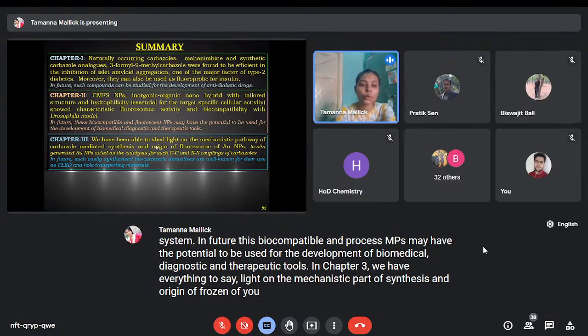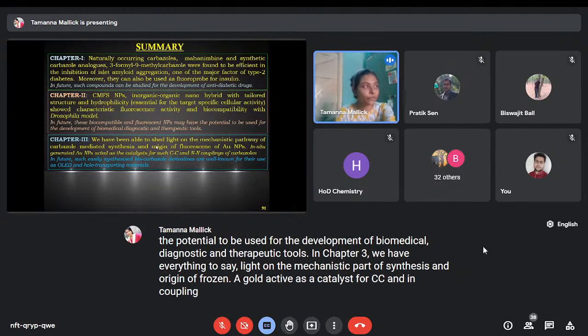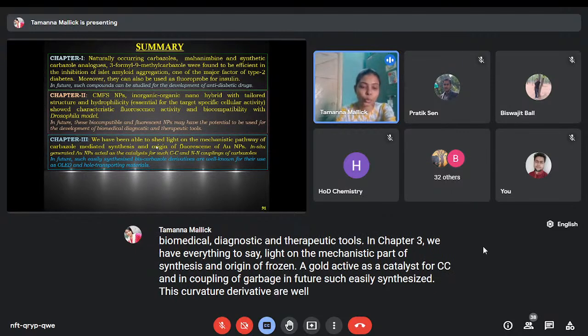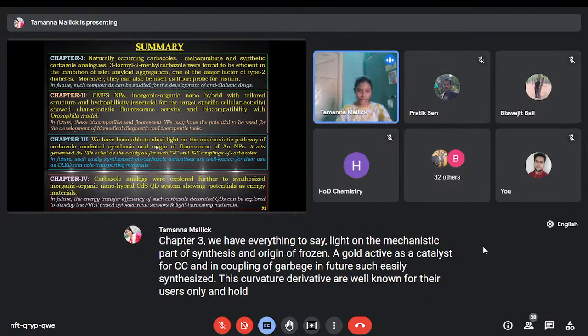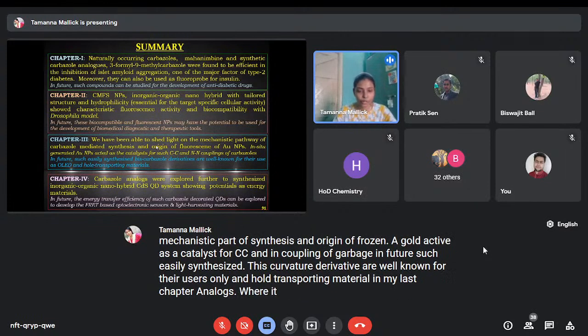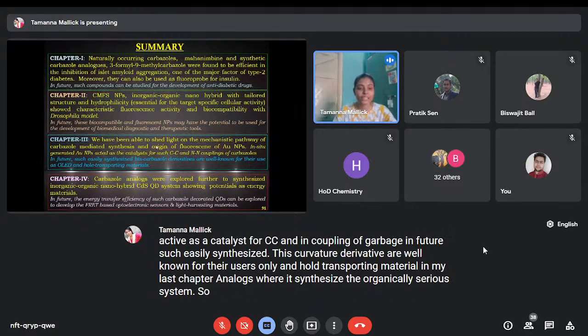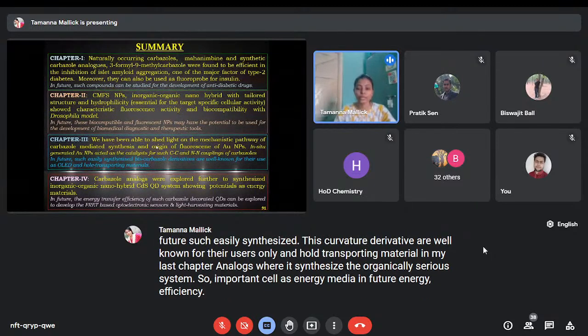Here, the in situ generated gold nanoparticle acted as a catalyst for such C-C and N-N coupling of carbazole. In future, such easily synthesized biscarbazole derivatives are well known for their use as OLED and hole transporting material. In my last chapter, carbazole analogs were explored further to synthesize the inorganic-organic nanohybrid CdS quantum dot system showing potential as energy material. In future, the energy transfer efficiency of such carbazole decorated quantum dots can be explored to develop FRET-based optoelectronic sensors and light harvesting material.